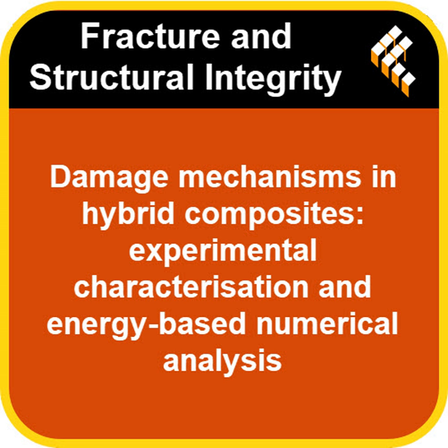What's also interesting is that the layers in the middle of the composite showed the least amount of damage, with one particular layer, often layer #4 in their 8-layer setup, being the least affected. Like a neutral zone almost. Kind of, yeah. They also confirmed that having more glass layers overall meant less intralaminar damage accumulating before they reached that peak bending force.